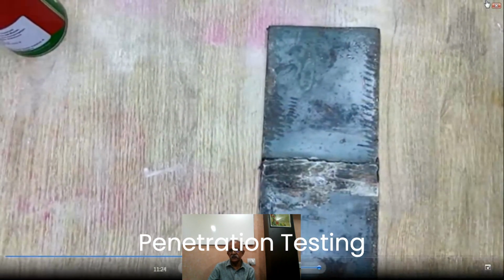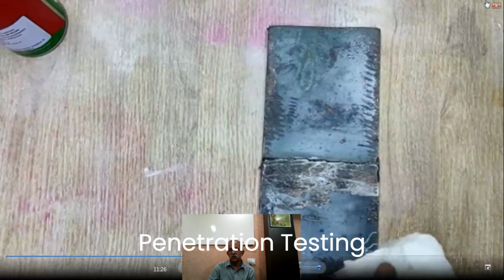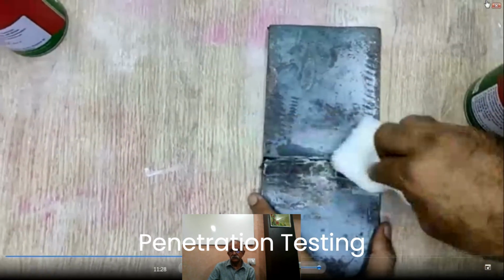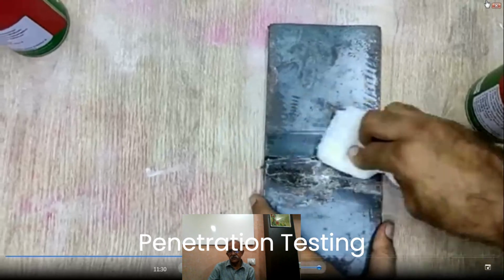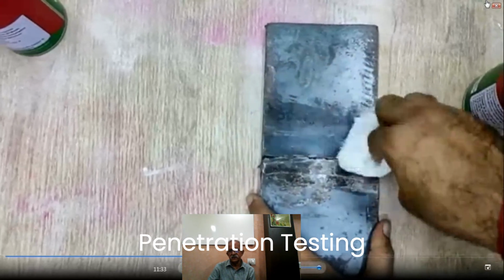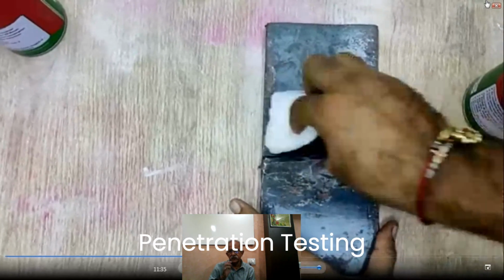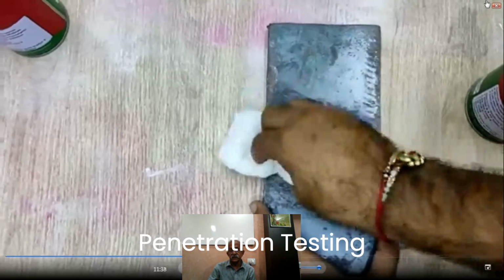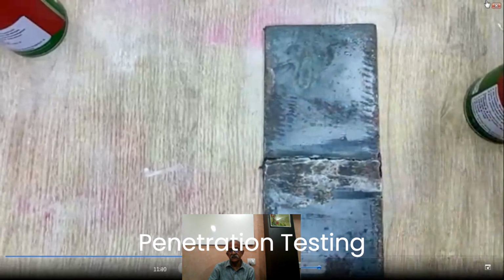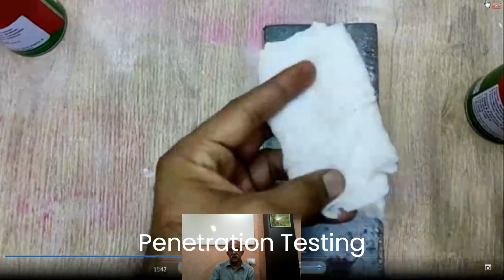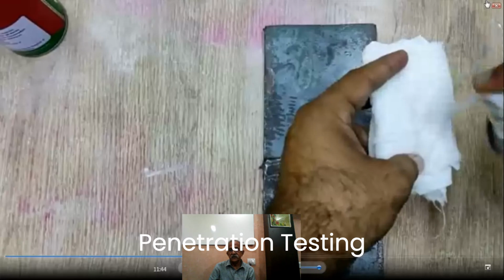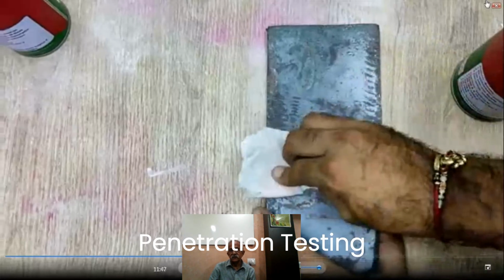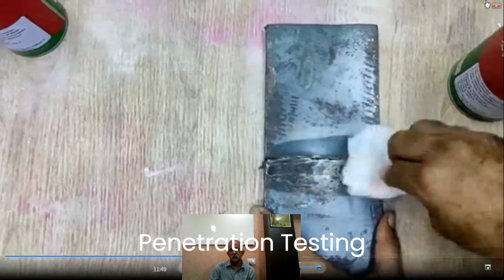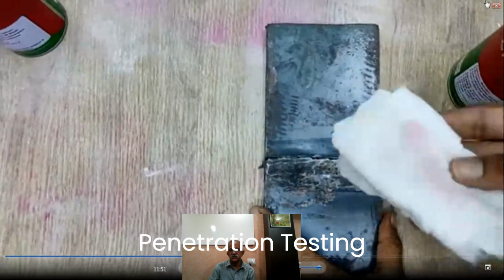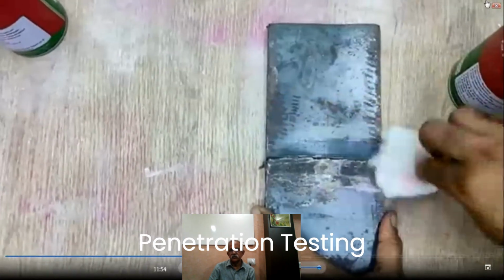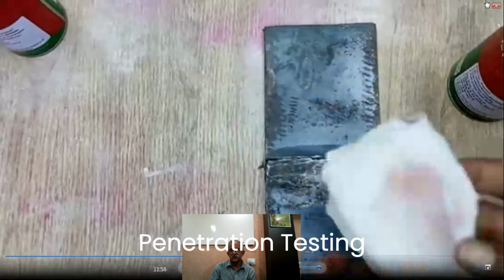So you have to take a lint-free cloth, a clean cloth, as you are seeing in the video. You have to see that it is lint-free. It should not have lint, so that the lint does not get entrapped into the defects, and then create a problem. And the cleaning should be done in one direction only, that you should not rub the surface which is to be cleaned, and you have to do it continuously till you are satisfied.